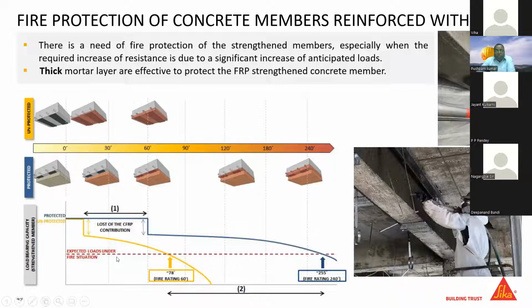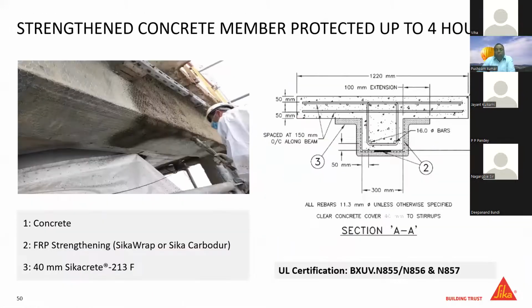Like this red line, you can see the minimum expected load carrying capacity, and up to 240 minutes, like for 4 hours, the strengthened section was able to take the desired load. On the left hand side photograph, you can see the beam section, the concrete section, installed with carbon fiber wrap and the carbon laminate at the bottom. This section is exposed to fire and tested. This testing is done as per UL guidelines.